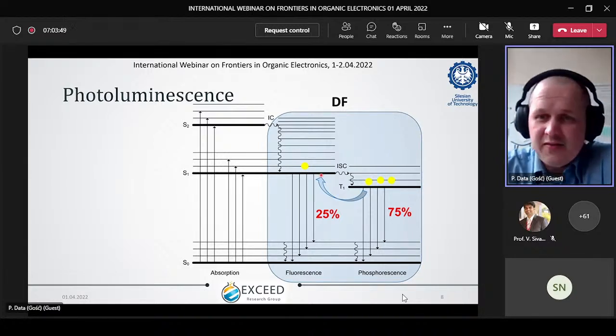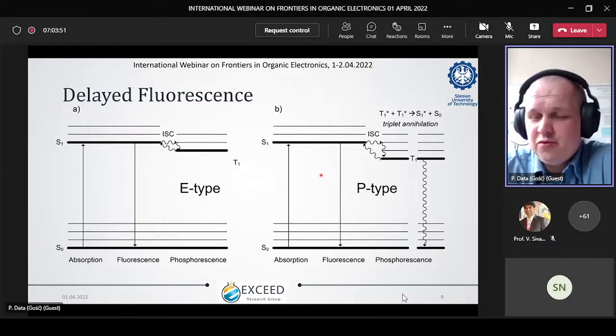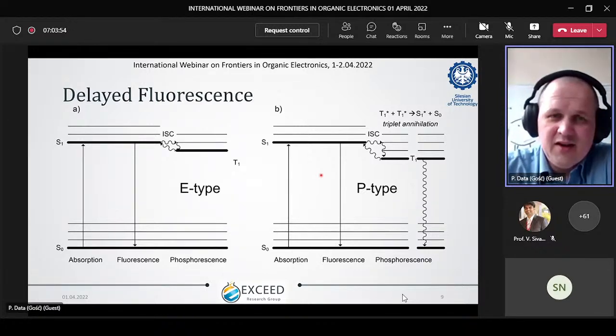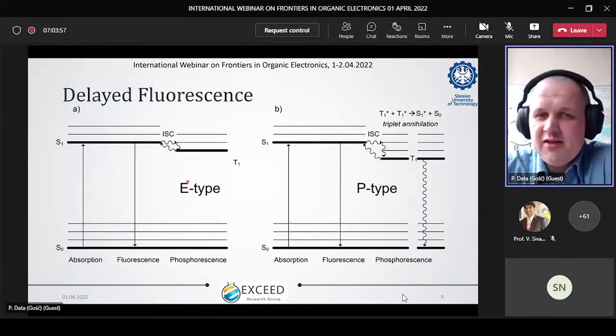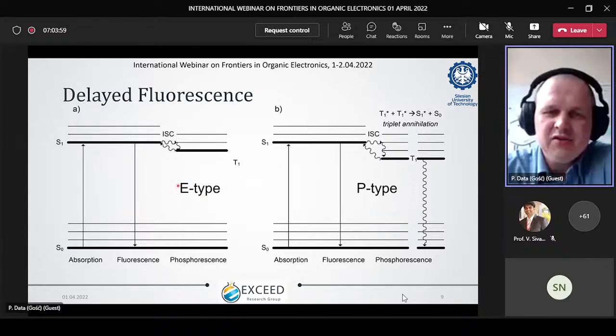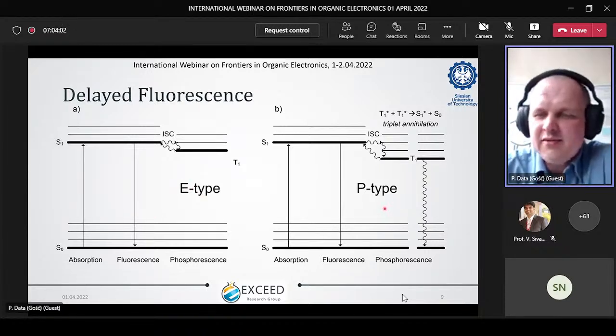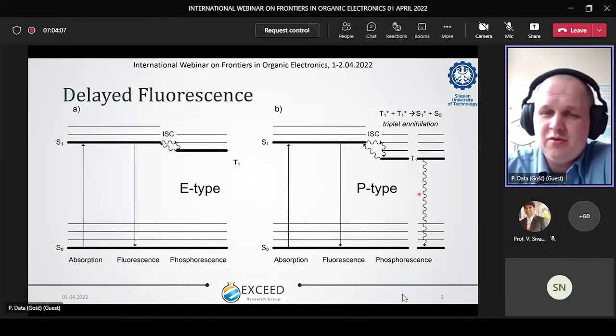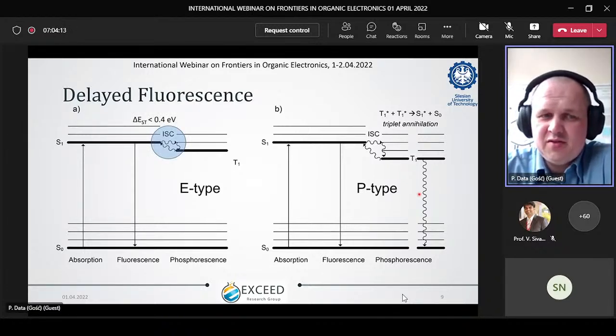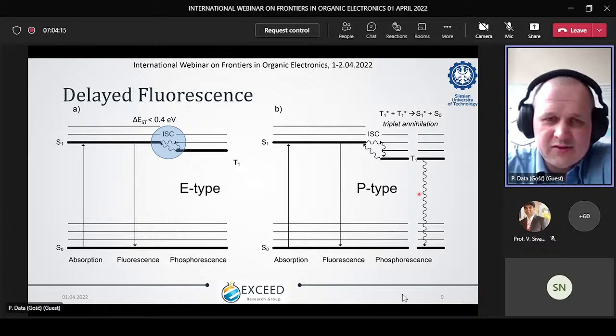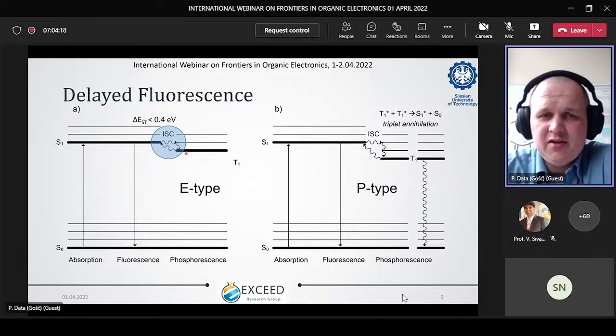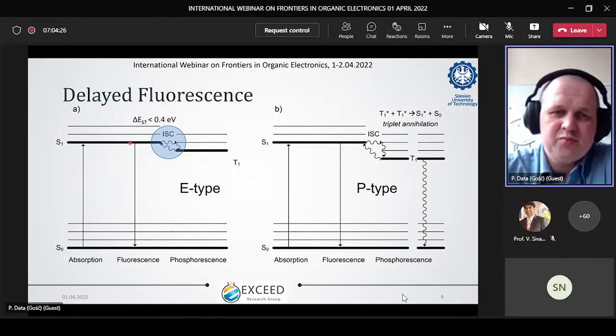Nevertheless, like everything in life, it's not so simple, because we have two types of delayed fluorescence process. One is called E-type. E-type delayed fluorescence is from eosin, where it was first discovered, and the second is P-type. P-type is from pyrene, where it was also discovered. So what is the important factor here? Why is there a difference between those two delayed fluorescence types? In the first case, our gap between the triplet and singlet state needs to be as small as possible. They must be as close to each other as possible.